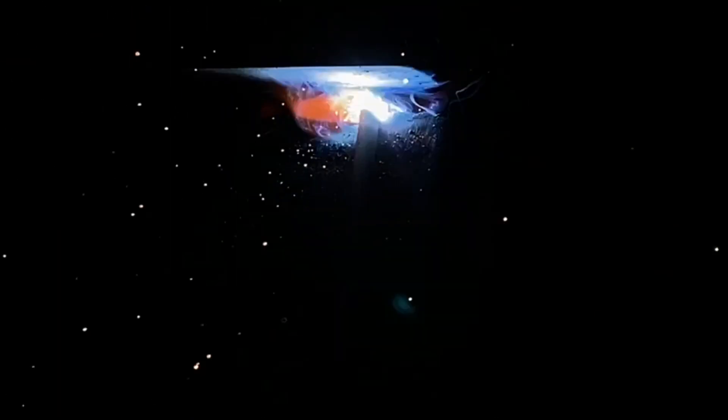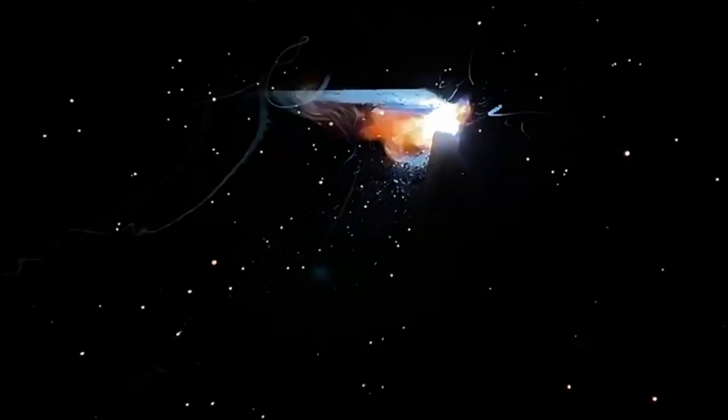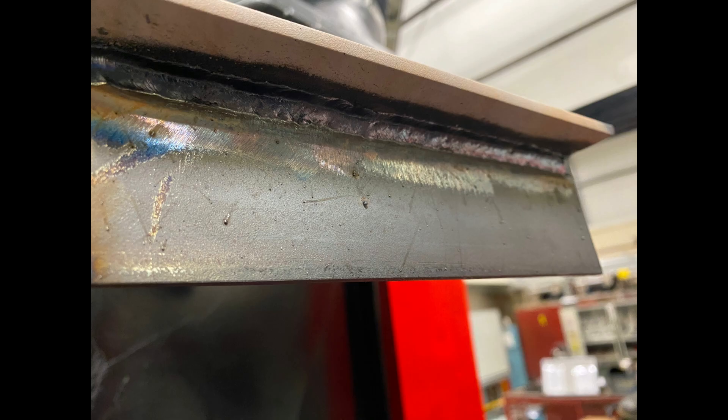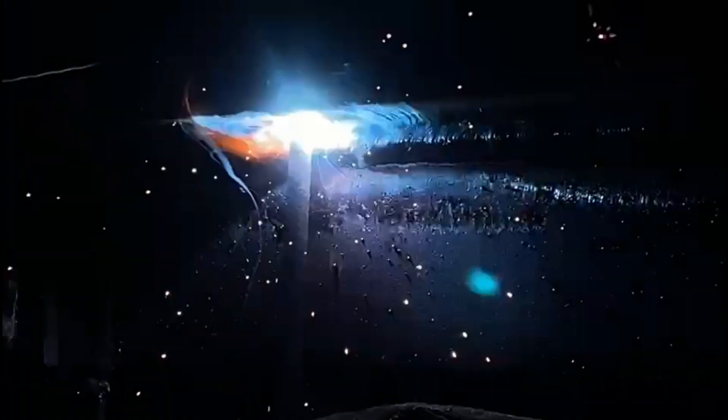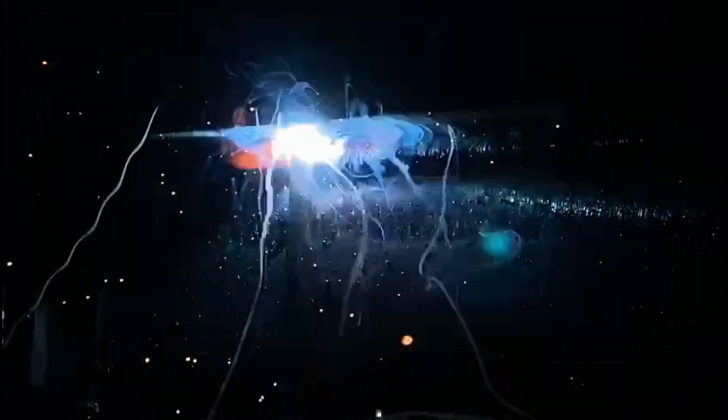This is the completed second run. Moving on to our third run, with this run we're trying to achieve the same distance along the top plate as we've achieved on the second run, so that our fillet is 45 degrees. If the second run is dropped too low, then we will struggle to achieve the right profile.